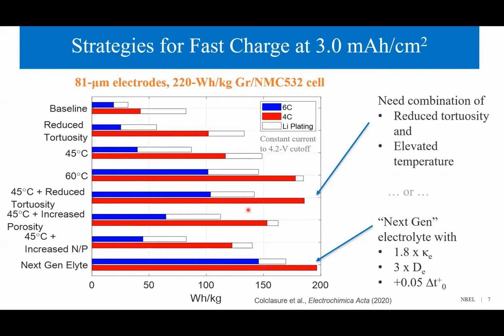The electrochemical model is used to investigate the various approaches to enable extreme fast charging without depletion for cells with a loading of 3 and 4 milliamp hour per centimeter square. This figure illustrates the model prediction for achievable energy density during 4C and 6C charging to 4.2 volts for cells with a loading of 3 milliamp hour per centimeter square. The white section of the bars represents where the model predicts depletion will occur.